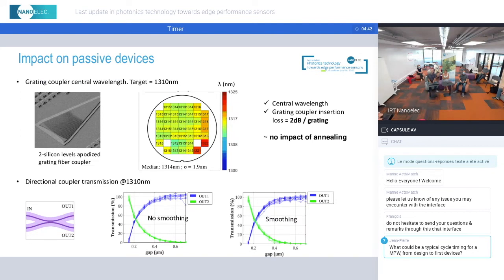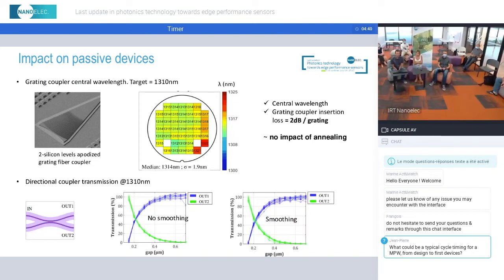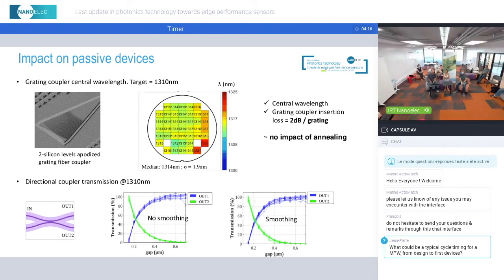Okay, so this slide shows you what happens when we apply the smoothing and annealing on two devices which are quite important. The first one is a grating coupler. It's very important to have good grating couplers to couple light in and out of the chip. One important parameter is the central wavelength of this grating coupler, and we target, for example, 1310 in the O band. You have a mapping of these central wavelengths measured on a wafer after annealing, and the median value is at 1314.